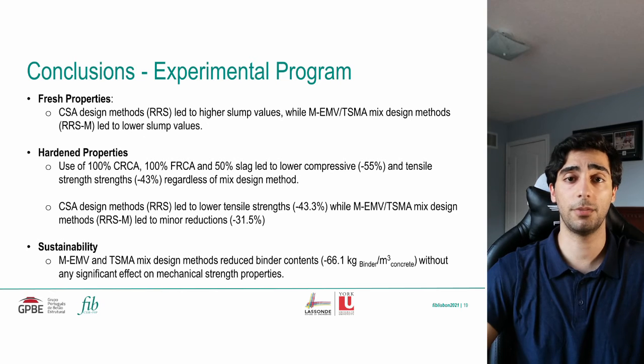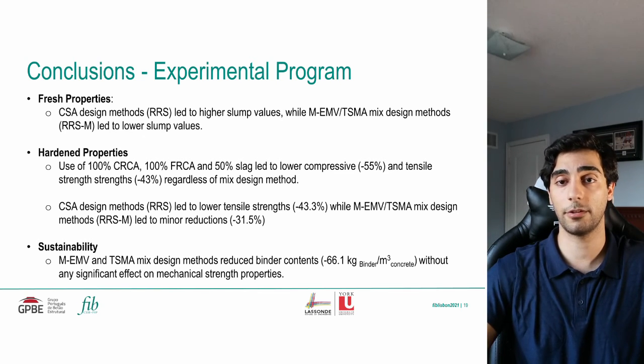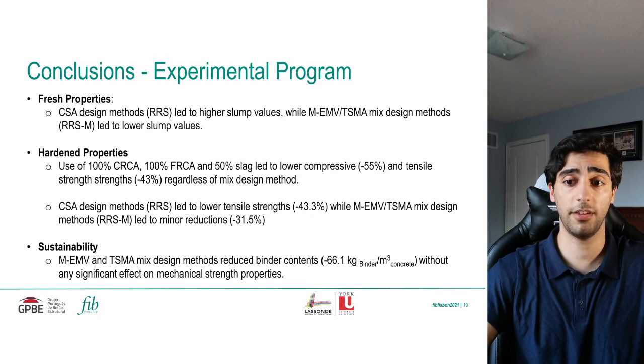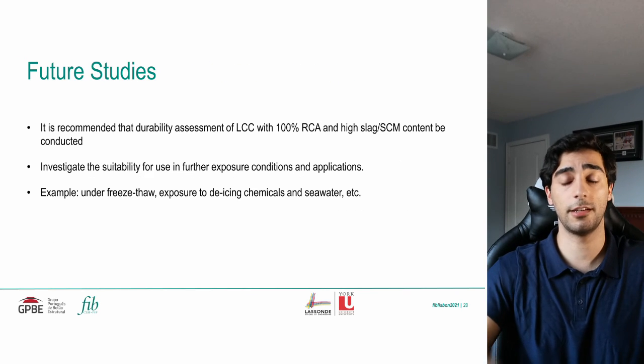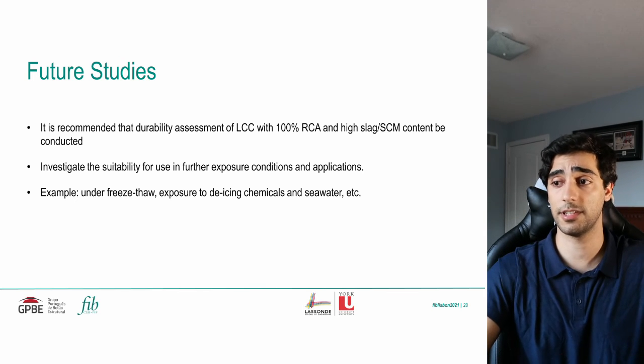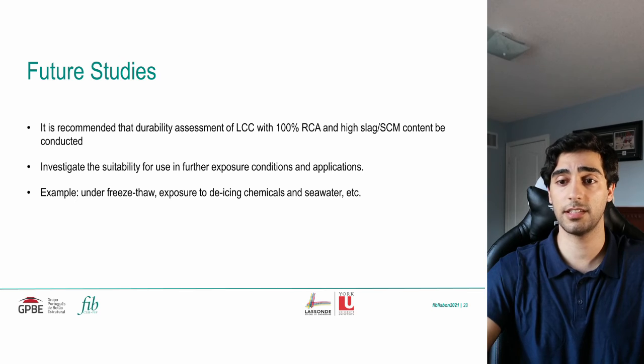In terms of sustainability, it should be found that the modified EMV and two-stage mixing approach utilize much lower binder contents compared to the CSA mix design methods, while having minimal effect on the mechanical strength properties and even improving tensile strength properties. In terms of future studies, it is recommended that the durability assessment of low-carbon concrete using 100% RCA and high slag or SCM contents be conducted in future studies. It's recommended that they investigate the suitability of these low-carbon concretes in further exposure conditions and applications, such as under freeze-thaw exposure, exposure to de-icing chemicals, and seawater.